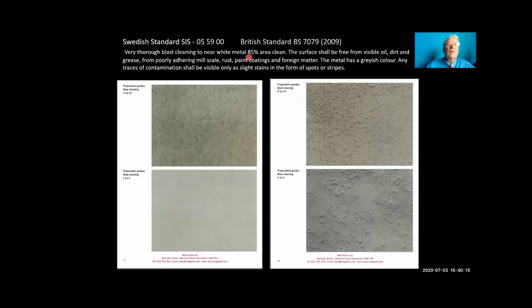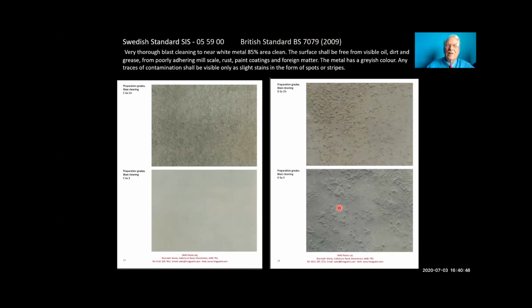So this is a rough surface that's 85% clean, and that is a smoother surface that's 85% clean. Or have I got, no, sorry, the wrong way around. That's the rougher surface. So these are the standards we're aiming at. If you want to be really perfectionist, you can go to SA 3. There we are. And that is a smooth and a rough surface SA 3. It's 100% clean. But it's been found that it doesn't have much benefit. It's much harder to do this. Getting rid of that last little bit of rust is actually quite time consuming, and it doesn't have that much effect on the paint. So the industry uses SA 2.5 standard for cleanliness.